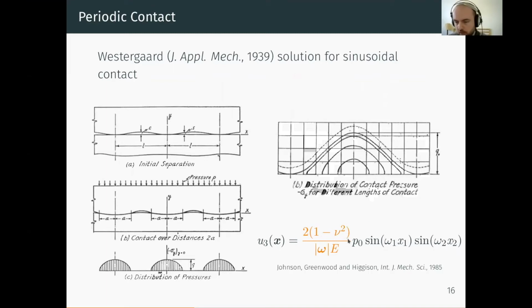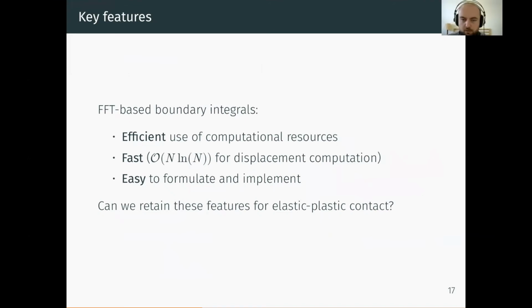And this coefficient here can be generalized to 2D if you have a 2D surface. And you can very well imagine how this can be efficient in the computation of a convolution integral, because using methods such as the fast Fourier transform, you can decompose contact pressure into a set of modes, apply this coefficient to each mode, and then recompose your equilibrium surface displacements using the inverse Fourier transform. So those are, in a sense, FFT-based boundary integral methods. They're very nice for elastic contact because they're really efficient. They focus all of the computational resources on the interface. We don't discretize anything inside the volume of the bodies in contact. They're really fast because of the fast Fourier transform, and they're rather easy to implement because fast Fourier transform libraries are readily available. So when I set out for my PhD, my initial goal was to try to retain those features to do elastoplastic contact.